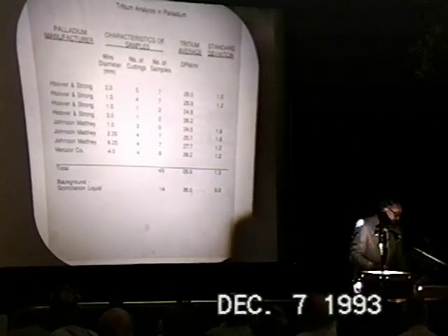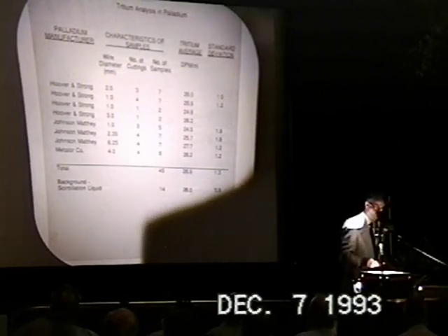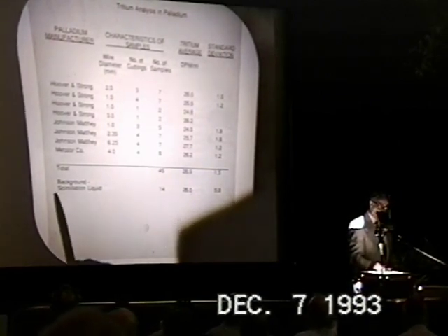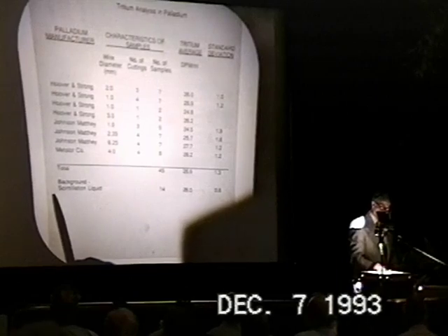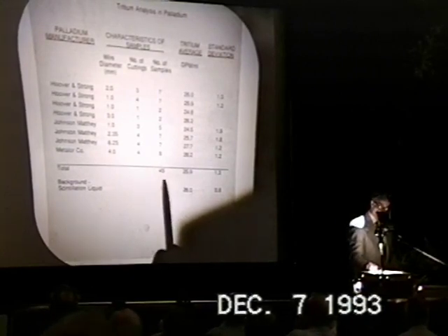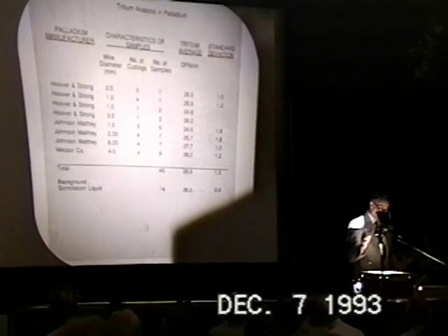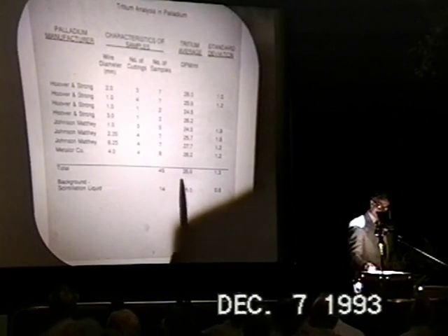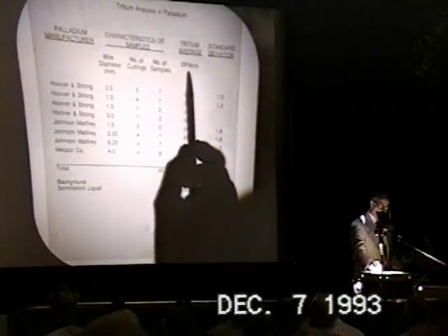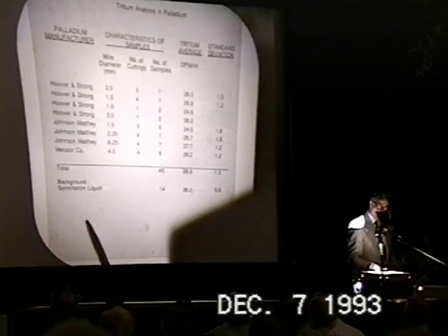These are previous results we have obtained, which I want to show very quickly to indicate how many background samples were known. These are results all obtained on as-received palladium. In this case, we analyzed a total number of 45 palladium pieces, and we are given the disintegrations per minute per milliliter, 25 with a standard deviation of 1.3.